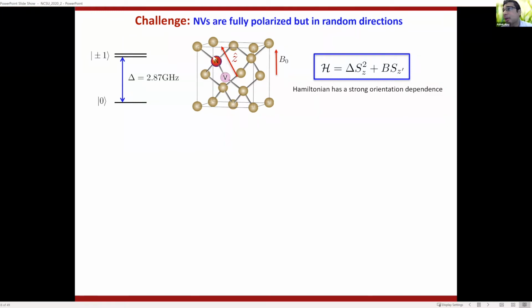So it turns out that when you shine light on these particles, they polarize in a direction given by this N to V axis. And this is not so much of a problem unless you consider a large collection of these NV centers. If you have a large collection of NV centers, or a large collection of nanoparticles, then every nanoparticle has a slightly different orientation, and you cover the entire gamut of orientations. And so all these NV centers, while they're all polarized 100%, are polarized in a local axis that has no correlation with an external axis.